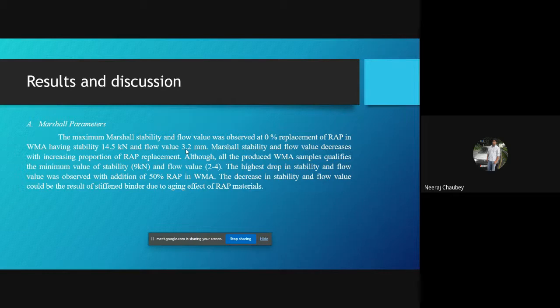The highest drop in stability and flow value was observed with addition of 50% RAP in warm mix asphalt. This decrease in stability and flow value could be the result of stiffened binder due to the aging effect of RAP material.